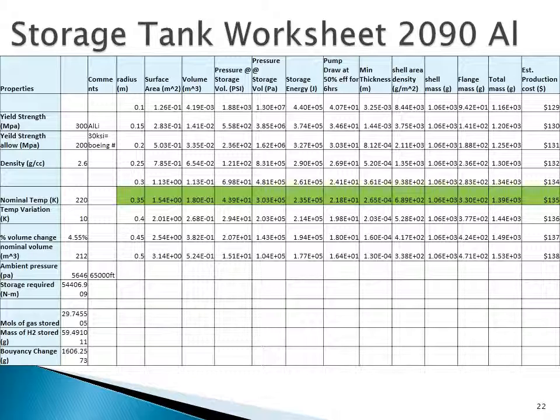In the worksheet I put together for the storage tank, if you had a 0.35 meter radius tank and a temperature variation of 10 degrees Kelvin for my balloon, then you end up with 44 psi in that tank. And to pump that over 6 hours during the day is 22 watts at 50% efficiency. So if you're at 25% efficiency, then you're at 44 watts draw, which is doable. And the total weight for this system out of a 2090 aluminum lithium is 1.4 kilograms. In my weight spreadsheet, I booked that up to 1.8 to give myself a little extra margin. So there's already margin in the design. If anybody is interested and they actually want the data or the spreadsheets, I can send it to them.